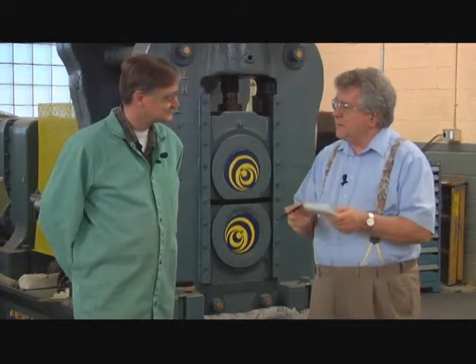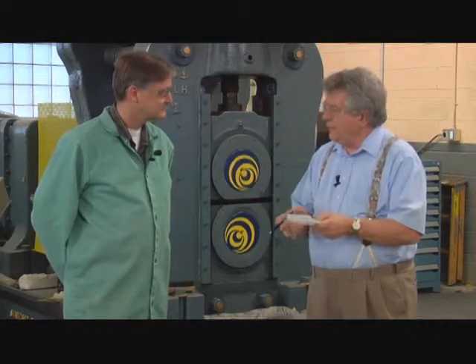From looking at the energy aspects of it, if we increase the operating temperature from 500 to 700 degrees or 800, wherever you can go with it, what's the effect of that on efficiencies and on the power plant operation? It's very substantial. The current power plants are operating at about 35% efficient, and with this increase in temperature and increase in pressure, the efficiencies are upwards of 60% or so. So that's quite a gain in efficiency, as well as a reduction in the amount of CO2 that's produced, for example.